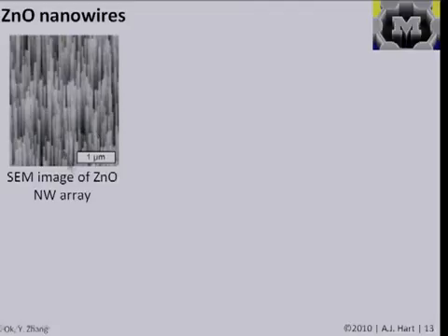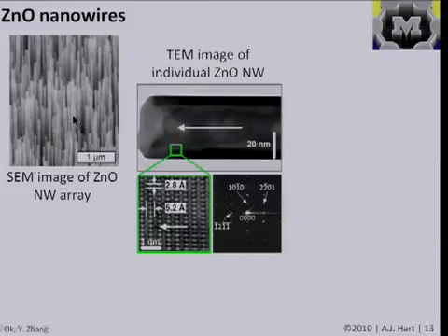And so these are individual nanowires that have a diameter of, say, a few tens of nanometers, and you can already see that there is a diameter distribution. Some are wider than others, and some are taller than others, indicating the non-uniformity in the process and how the growth rate may depend on the size. And if we imagine we were able to break this up and pick one of them out, we could look in a transmission electron microscope, and we could isolate an individual zinc oxide nanowire, and we could then use the techniques we'll learn about next time to look at the structure.